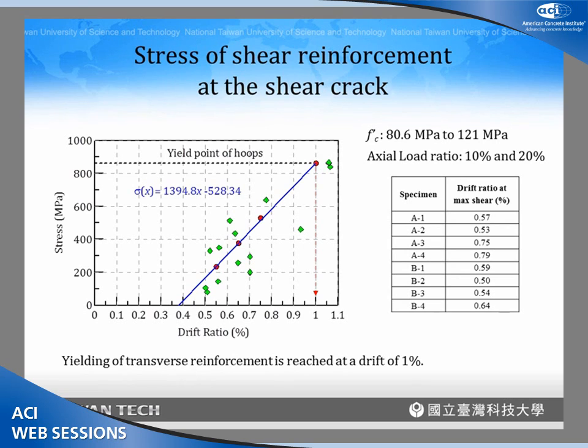And this slide shows you a very interesting observation that we got from the strain gauge readings. From the strain gauge readings, we found that the maximum strain in the transverse reinforcement at the crack is positively correlated with the drift. So we found that after the shear cracking, the higher the drift ratio, the higher the stress in the transverse reinforcement at the crack. And we found that in order to get the yielding of the transverse reinforcement, we needed a drift ratio of approximately 1%. So before 1%, if the column fails, you don't get the yielding of the transverse reinforcement.